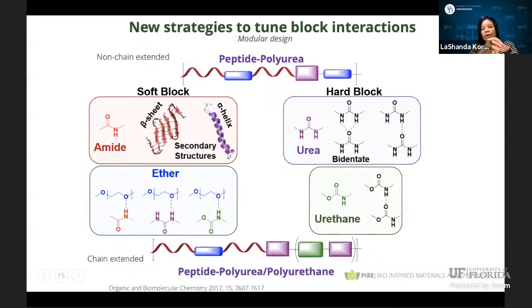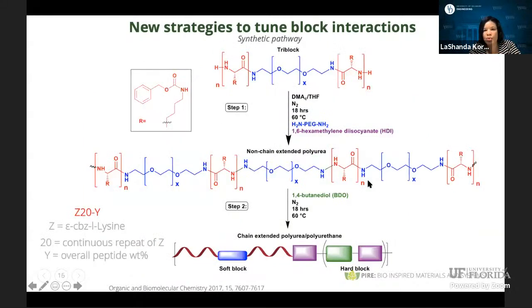So we wanted to now think about, can we tune this soft block such that we can promote either hard and soft block interactions or interactions between the soft block components. So we wanted to now switch to a polyether system, again polyethylene glycol, which could have associated behavior with either the soft block peptides or with the hard block. So in this case, we turn again to creating our tri-block structure, polyethylene glycol as our middle block. And then here we're using lysine. I can just say in advance, the application for this was gels that we could use for biomedical applications. So that's why lysine gives us some tunability with environmental conditions.